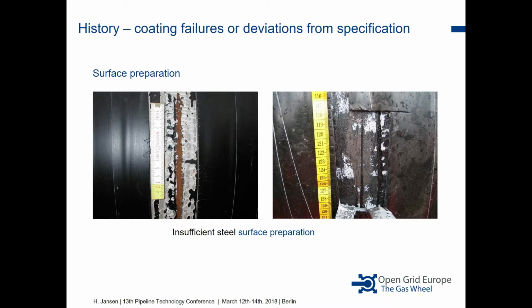This is typically what we find when the surface preparation is not done properly. Surface preparation involves two issues we try to achieve. The first is cleaning of the steel surface, and the second is getting the correct roughness of the steel surface, so that we get the best adhesion between the coating system and the steel surface. On the left photo, you can see that no preparation was done at all. In this area there was a peel test, and the peel test shows a full adhesive break.